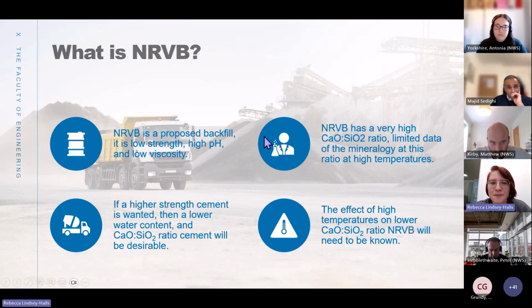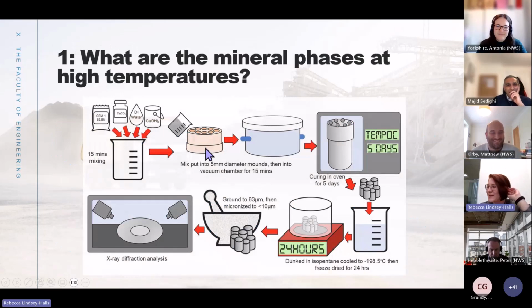So this is the methodology that I've been following to look at the first aim, which is what I'm going to talk about today. The 4 components are mixed for 15 minutes until you get a homogeneous mixture. We've then developed with the technicians here these various molds. These are important because with the cements, you get little 5mm cores out at the end. So you don't need to use any machinery that could increase the heat of the cement, or if you need to use coolant, this can contaminate the sample and also make other reactions take place. So you're getting out exactly at that time point the products that you're forming.